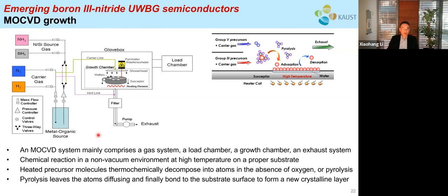So here is a basic diagram of an MOCVD system. It comprises a gas handling system, a load lock chamber, a growth chamber, and the exhaust system. The chemical reaction happens in the growth chamber, as shown right here. So basically, under high temperature, the precursors, for example trimethyl aluminum, will decompose into atoms in the absence of oxygen, a process called pyrolysis. And this pyrolysis lets the atoms diffuse on top of a heated substrate and then bond to each other to form a new crystal layer, atom by atom. Right? So it's an epitaxial process.